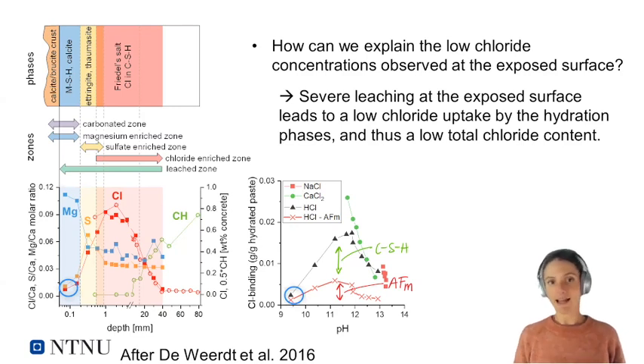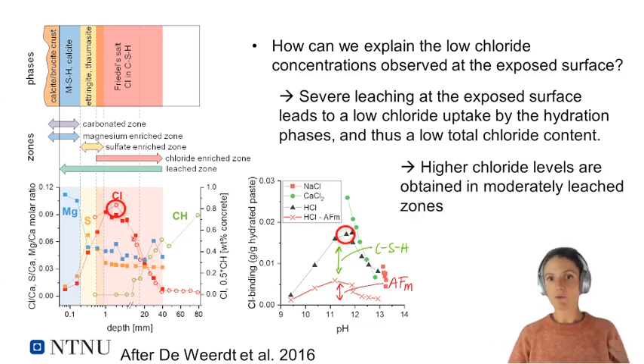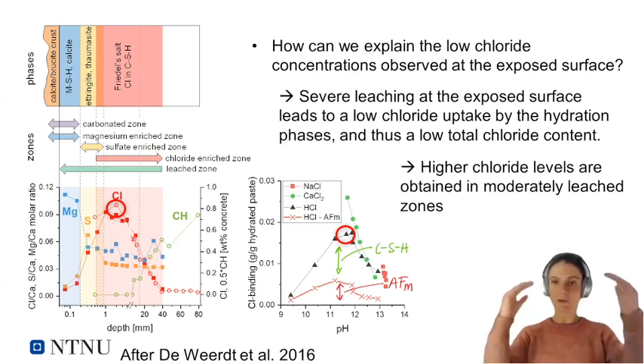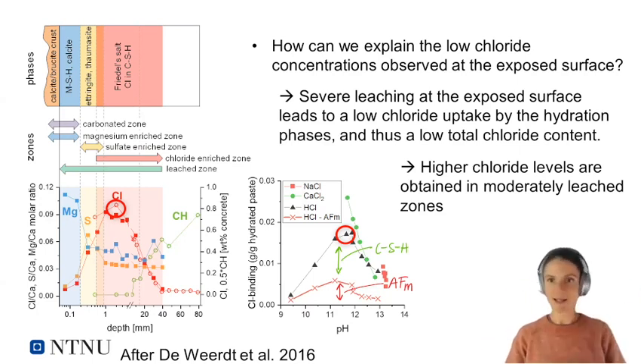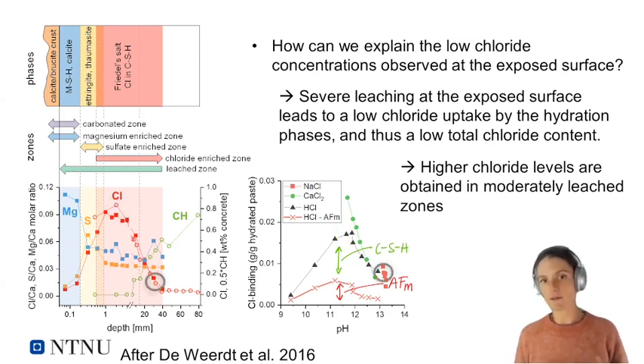What we can see at the surface, where we have this magnesium enrichment, is a low pH, a pH towards 10. This means severe leaching, and when we have such severe leaching, our hydration phases are not able to take up any chlorides anymore, and we have a low total chloride content. Though when we move slightly deeper in, we have moderate leaching, and we actually have an enhanced chloride binding, explaining why we have these higher chloride levels slightly deeper in. And if we move even deeper in, our chloride binding is not as much affected by leaching anymore, and we come closer to chloride binding values which we would observe for sodium chloride.